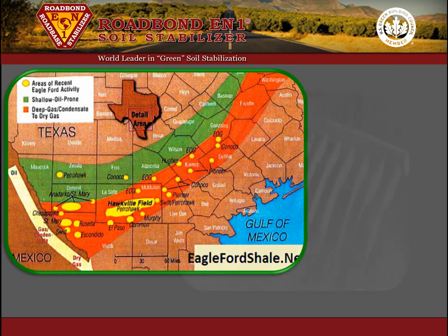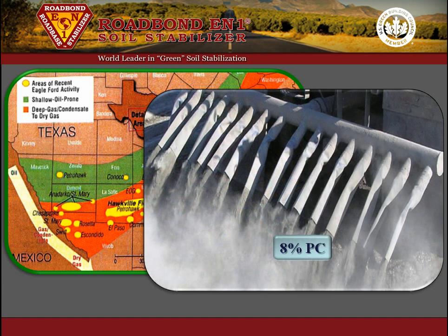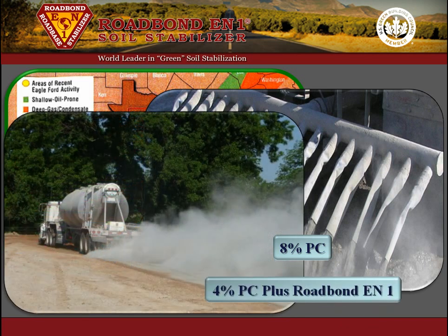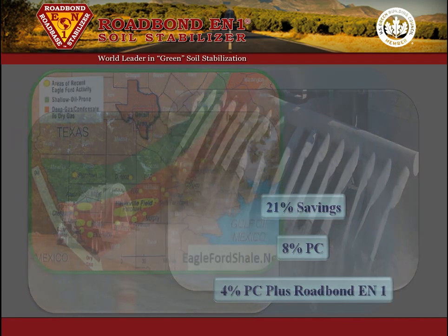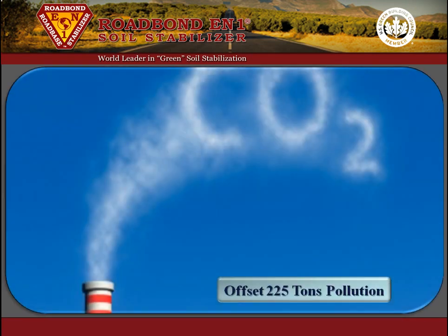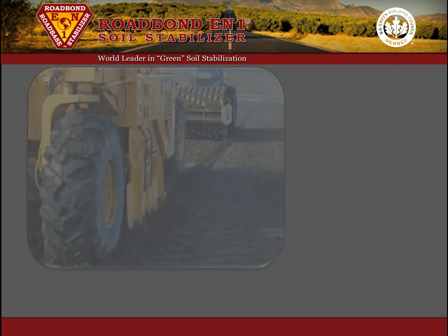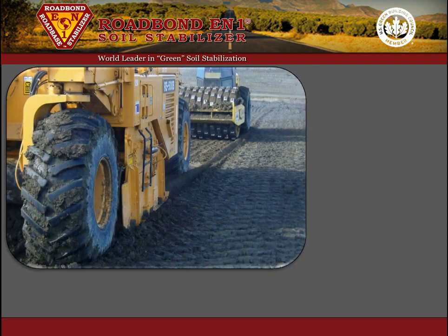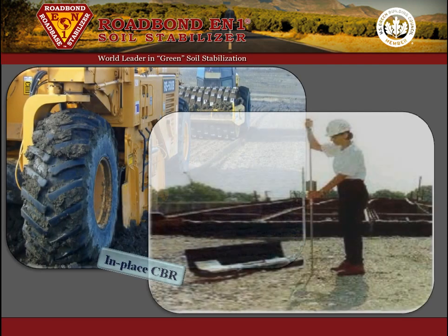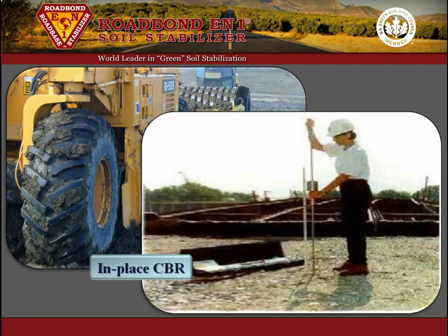Field evaluations were conducted in the Eagle Ford Formation south of San Antonio, Texas. One location was stabilized as usual, with 14 loads of Portland cement, while a neighboring location was stabilized with only 7 loads of Portland cement and Roadbond EN1. This saved 21% of the cost of the stabilization materials and offset over 225 tons of greenhouse gas. Both locations were tested for strength 14 days after construction and then again about 45 days after construction.